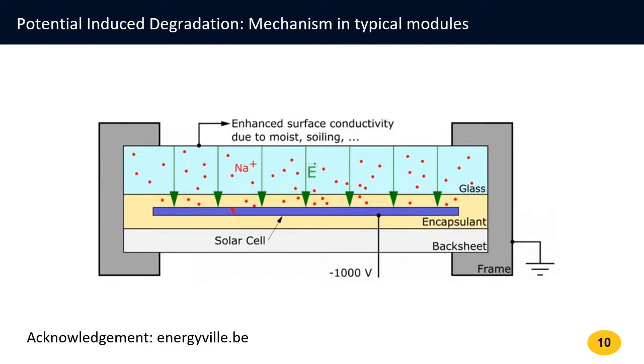It's also dependent on the anti-reflective coating, and including some cells. In fact, your multicrystalline or polycrystalline is more likely, if I'm not mistaken, to be afflicted, at least with specific types of defects, due to the fact that it's got actual grain boundaries in which the positive ions can more easily migrate through, causing obviously issues with regards to shunting or increased defect-related recombination.